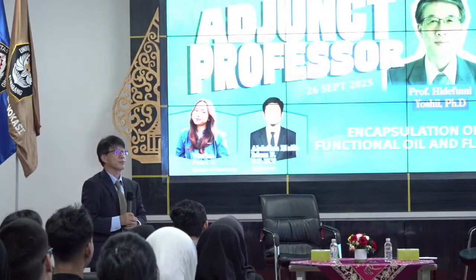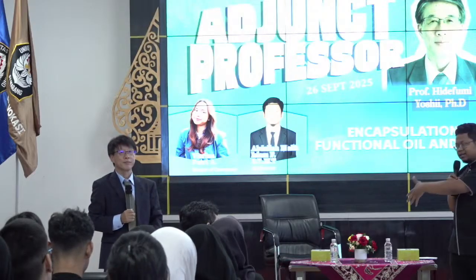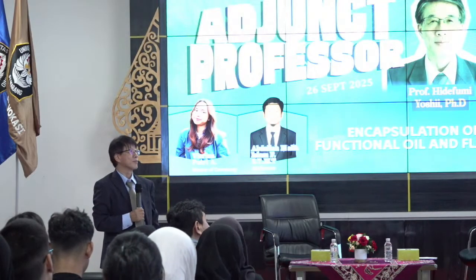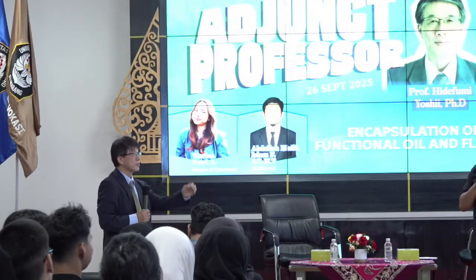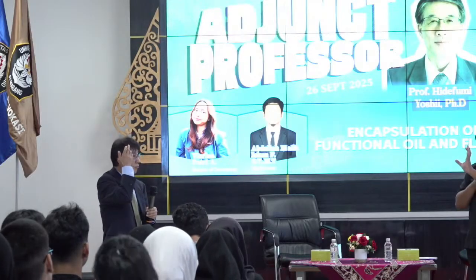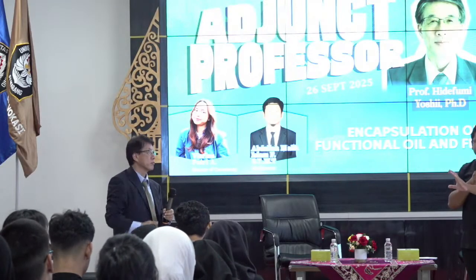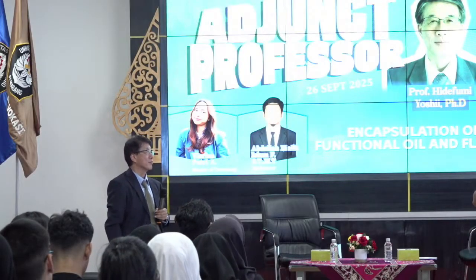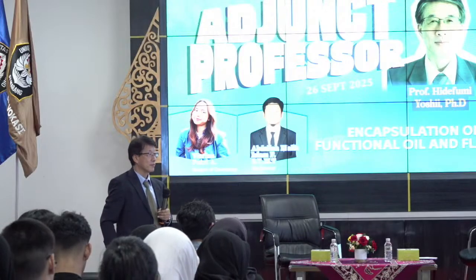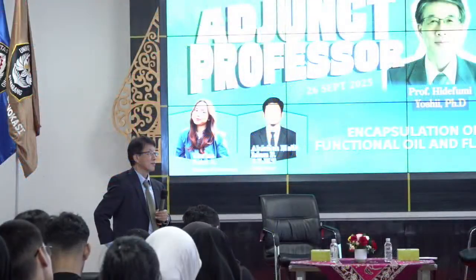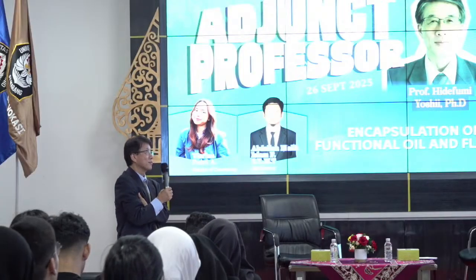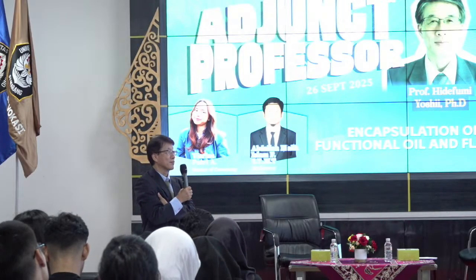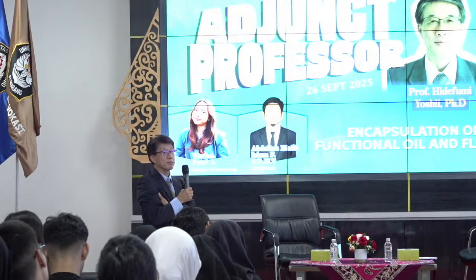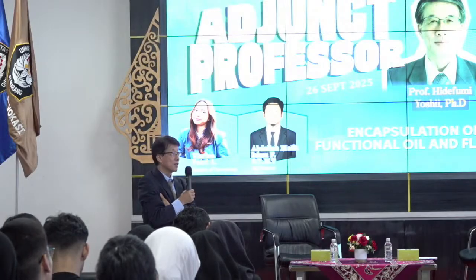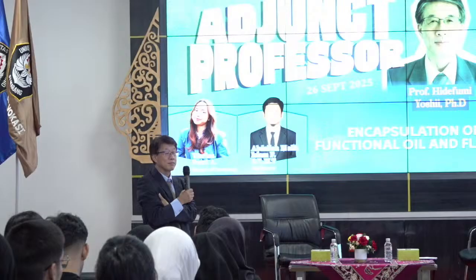I would like to explain a little more. Yoshii-sensei said that if you want to do spray drying, especially for encapsulation, please give attention to the glass transition temperature. And if you want to operate the spray dryer, you should have something like a cooling jacket too, because the stainless steel of the spray dryer can rise in temperature up to 200 or 300 Celsius. Please use a cooling jacket.